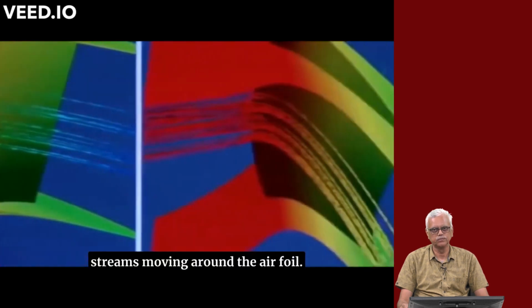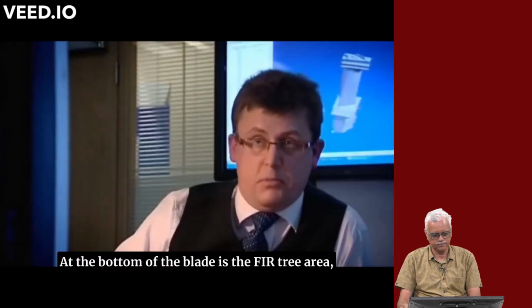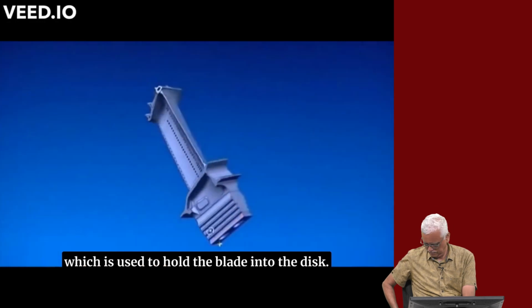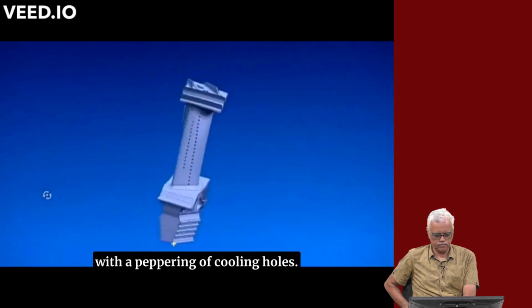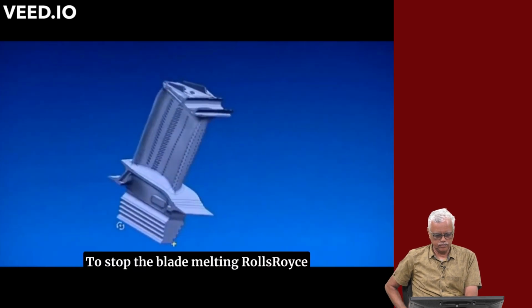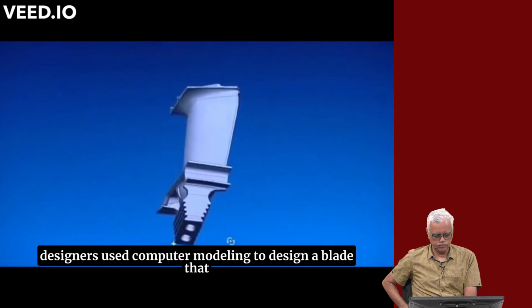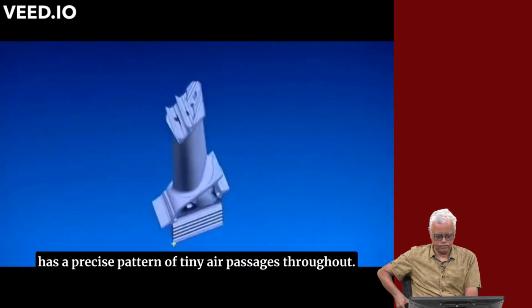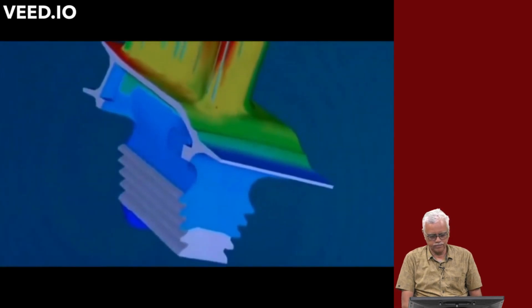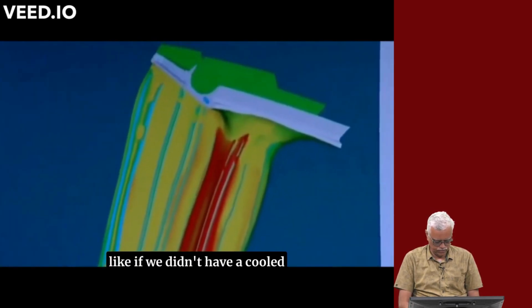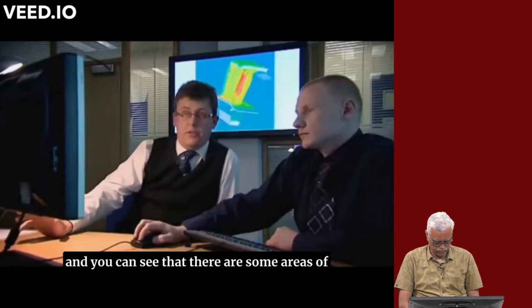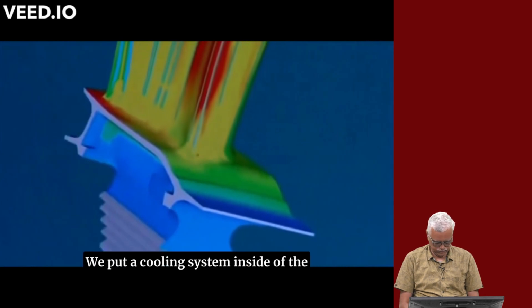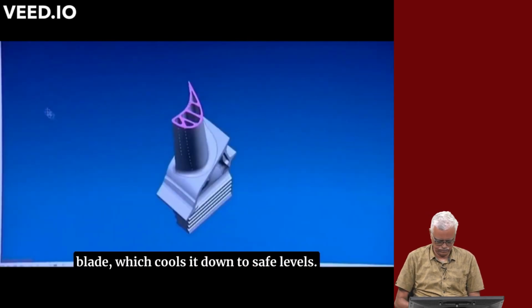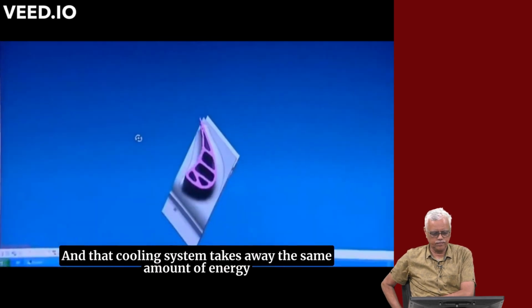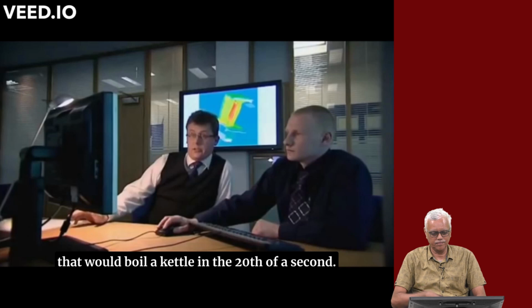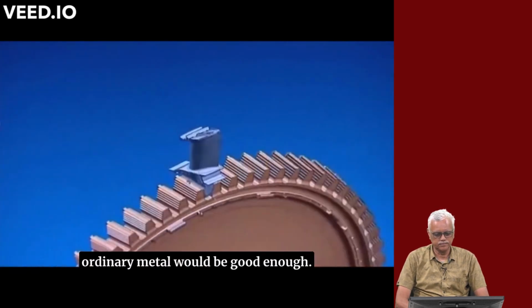Here you see the gas streams moving around the airfoil. At the bottom of the blade is the fir tree area, which is used to hold the blade into the disc. Above it you see the aerofoils with a peppering of cooling holes. To stop the blade melting, Rolls-Royce designers used computer modelling to design a blade that has a precise pattern of tiny air passages throughout. Here we see what the blade would look like if we didn't have it cooled. And you can see that there are some areas of red, which means that the component is too hot. We put a cooling system inside of the blade, which cools it down to safe levels, and that cooling system takes away the same amount of energy that would boil a kettle in a 20th of a second. But even with the cooling holes, no ordinary metal would be good enough.